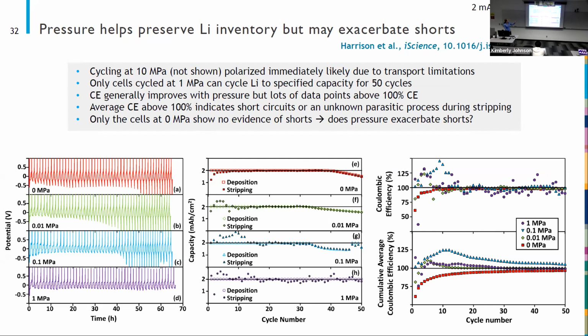We also see that the coulombic efficiency generally improves with higher pressure, but I'll note that many of those data points in that upper right-hand plot are above 100%, and that makes us really suspicious of short circuits. So I will say that we can have coulombic efficiencies above 100% in a cycle or two. That's okay, because you can get dead lithium that forms on one cycle, reconnects in another cycle, and then it'll be low on one cycle, high on the next. As long as it averages out to less than 100%, we're okay.